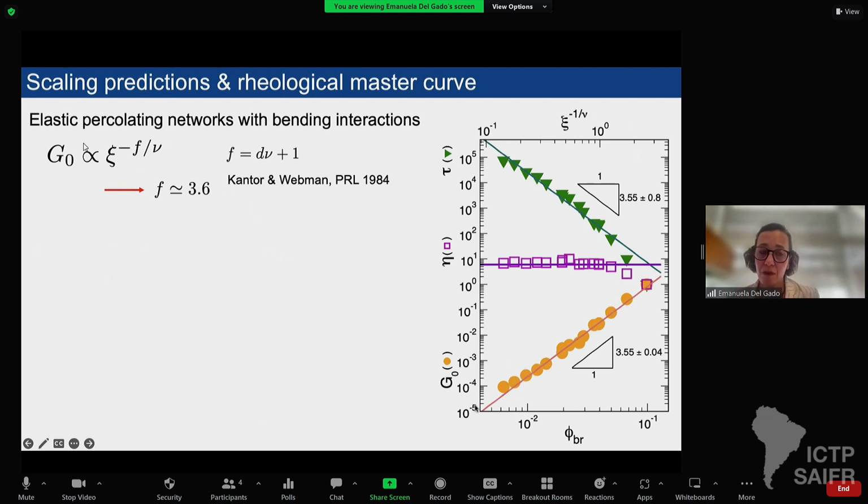So what I was introducing is basically the scaling of the modulus that I obtain here, which is predicted by this model. But what we find, which is a new result, is that this time scale that I use to rescale the x-axis in my viscoelastic spectra should scale in the same way. And there are some interesting ideas of why this happens. It's never been tested in experiments, so it's also an exciting prediction that comes out of looking at things in this way.